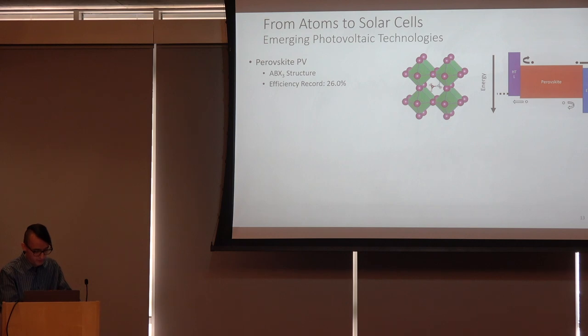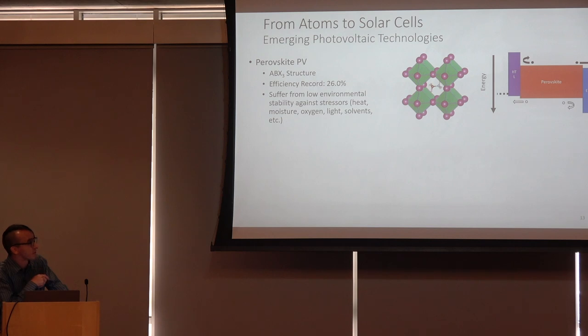And the efficiency record for these devices is 26.0%, so really close to the record silicon devices after comparatively much shorter development time. However, they suffer from low environmental stability against stressors, and I think it's safe to say that improving the stability of these devices is one of the central focus points in the field of perovskite photovoltaics.